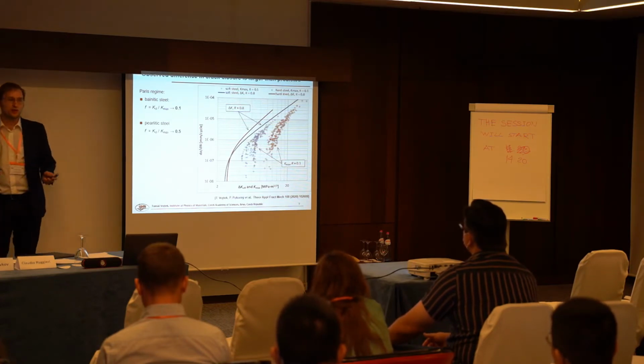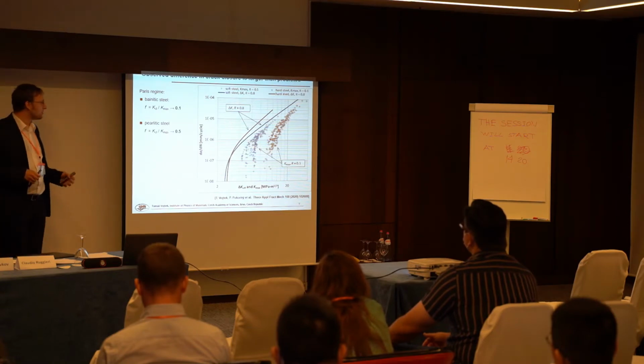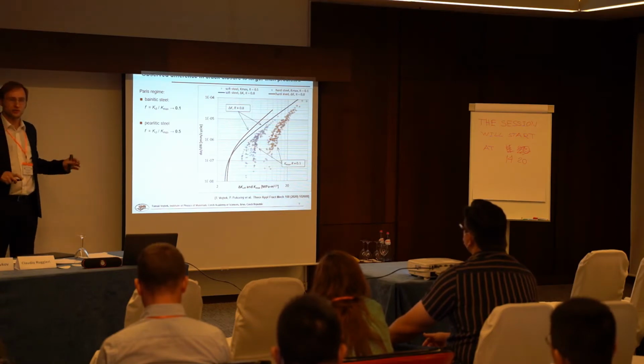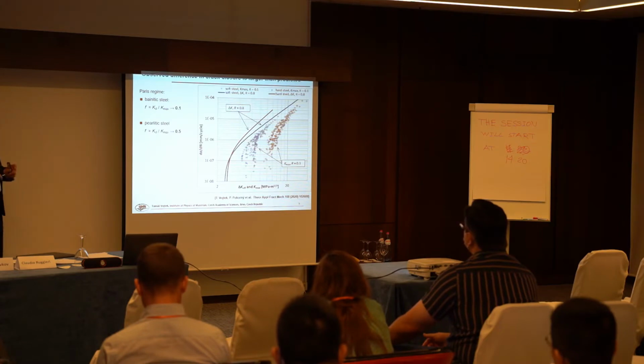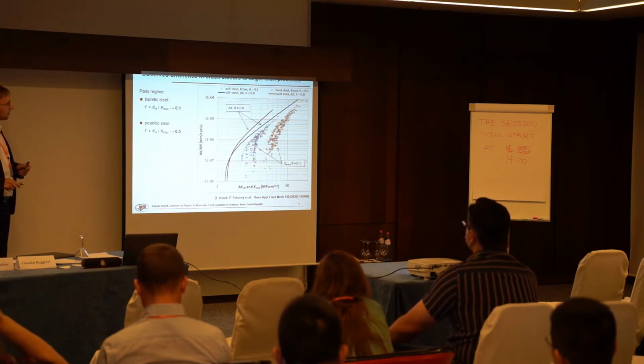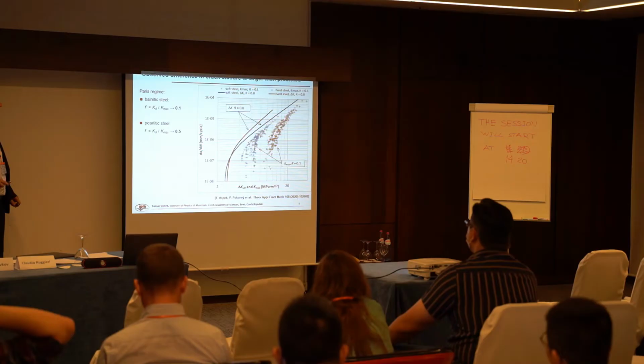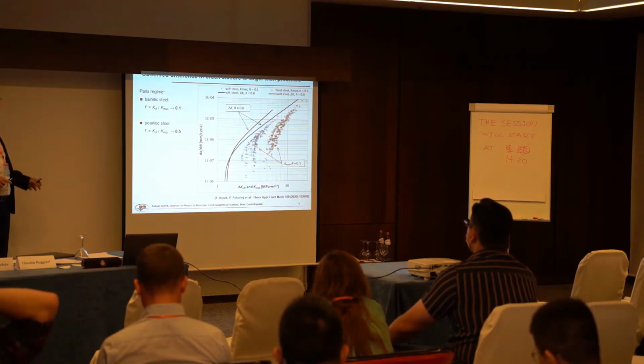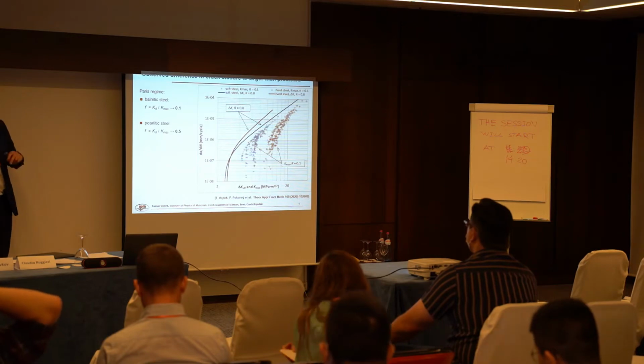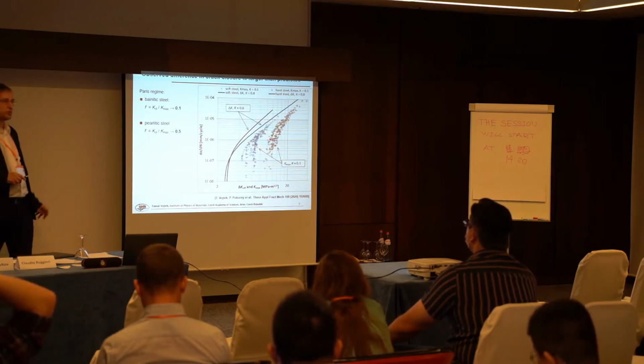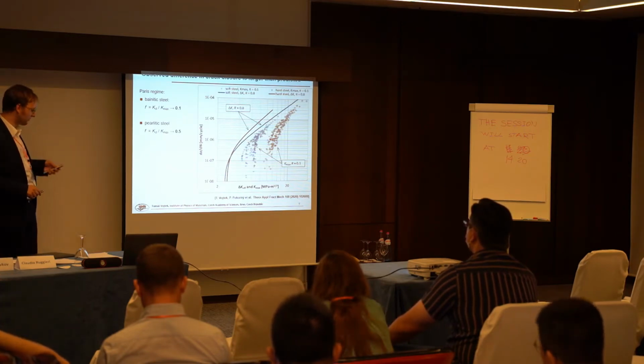And this cannot be explained by the plasticity induced crack closure value by the available models. So if we just calculate from this data, the crack closure ratio should be in one steel 0.1, in the other one 0.5. But the models always predict something about 0.25 or 0.3.